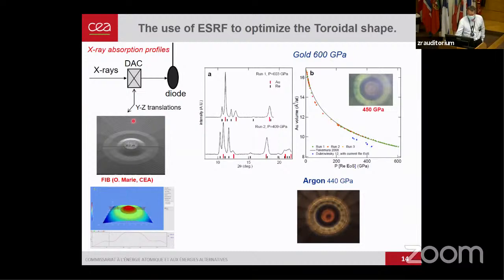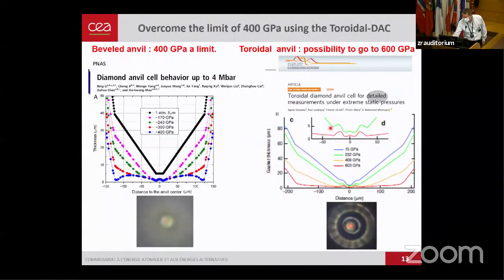And I like to say that the profile of these new anvils was made by measurements at the ESRF, where we had beam times to really scan the profile, do the measurements with metals, and really optimize this diamond tip. It's really like having the tip and then having this little other envelope on top of it, but it's part of a single crystal, so you can do exactly the same kind of measurements as in standard, with the same dimension of sample as in standard diamond cell. And I would like to show also that this type of diamond tip is deforming very well under pressure, and I will show you that you can recover your anvils even going to very high pressure.